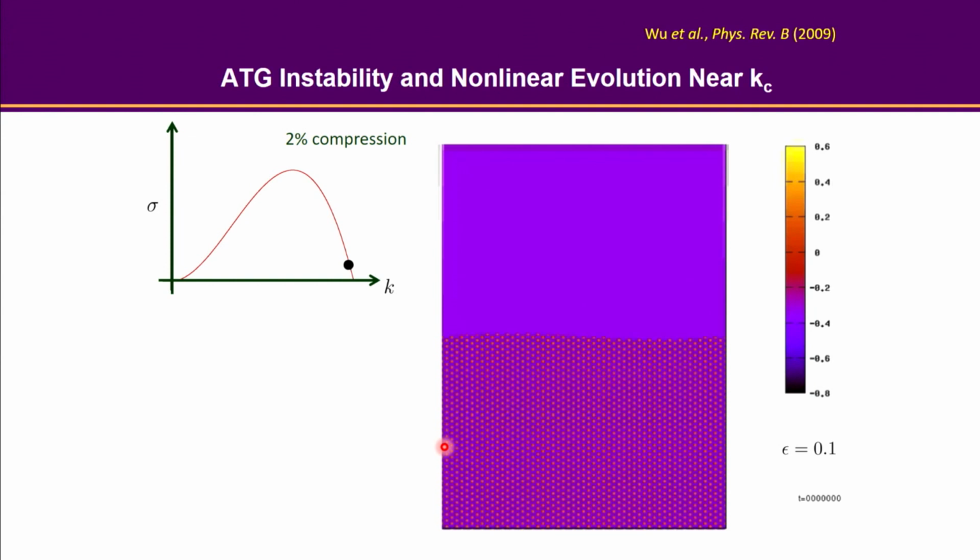You have to use the modified or reduced dimension, let's say Lx prime, and that will give you a new set of wave numbers. And if you're using that setup, the solid immediately becomes a stressed solid, right? Because the corresponding wave number would not be equal to 1, so they're going to feel the solid is being stressed.